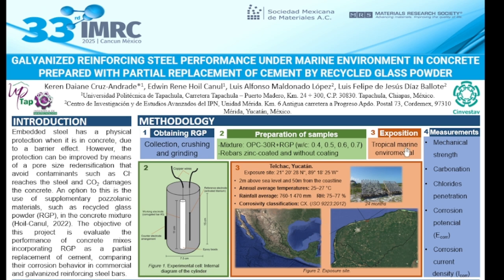In the third step, the samples were exposed for 24 months in Telchac, Yucatan. As you can see in figure 2, we have Mexico, Yucatan, and the site of exposition, Telchac. These are the coordinates of the exposure site. The site was 2 meters above sea level and 50 meters from the coastline, with an annual average temperature of 25 to 27 Celsius degrees. The rainfall average is from 760 to 1,470 millimeters, and the relative humidity from 75 to 77%, and